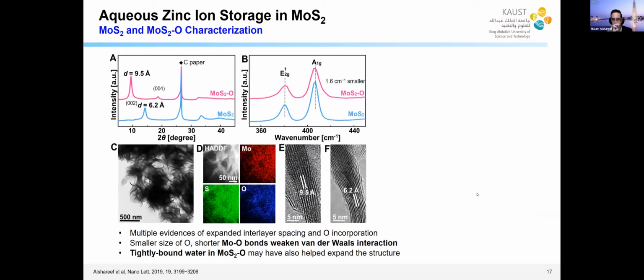So we characterized this. First of all, if you look at the TEM and you look at compositional analysis, you see that this oxygen substituted molysulfide, in fact, has oxygen. Oxygen is in the blue here, and moly is here, and sulfur. Another thing you see is that when you substitute the oxygen into molysulfide, the X-ray diffraction pattern is shifting to lower 2 theta. It means we have expanded the interlayer spacing. Basically, the moly-oxygen bonds weaken the van der Waals interaction between the molysulfide layers, and this allows you to expand the interlayer spacing.